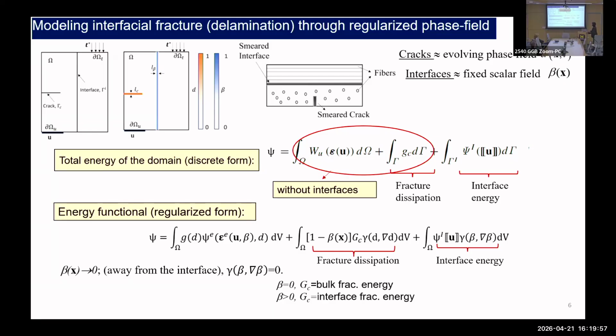Okay. And then if you look here, the two important parts, we have this 1 minus beta term sitting in this fracture dissipation term. So what does this do? This is basically controlling the interactive crack propagation between the interface and the bulk. So if beta is 0, then you are actually in the bulk. So correspondingly, Gc will be the bulk fracture energy or the lamina level fracture energy. And if beta is non-zero, Gc will be the interfacial fracture energy.